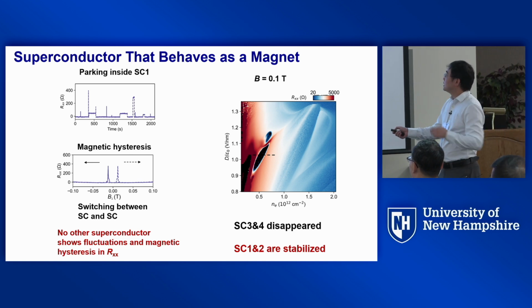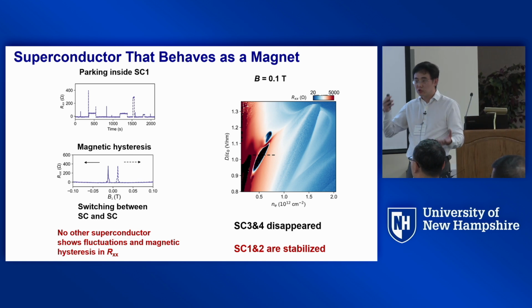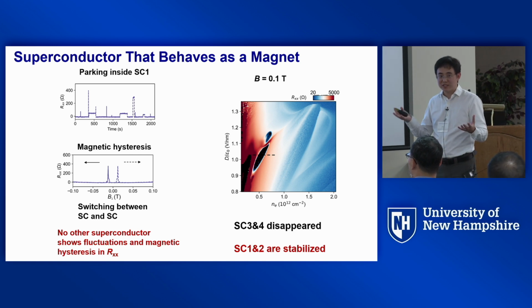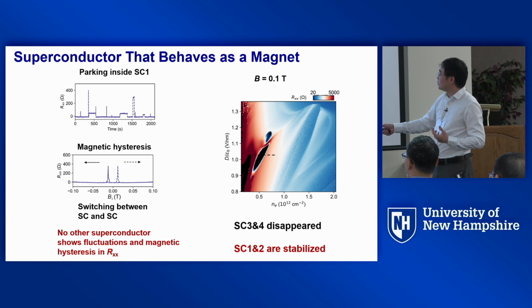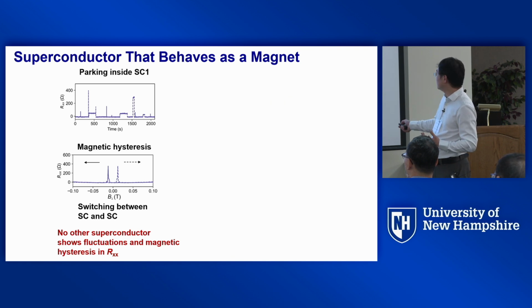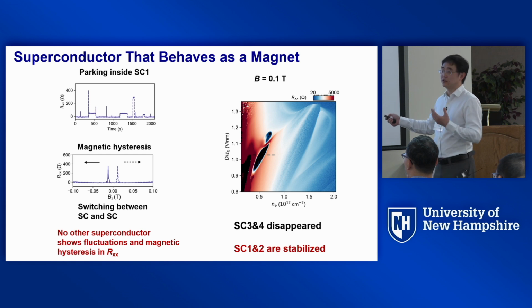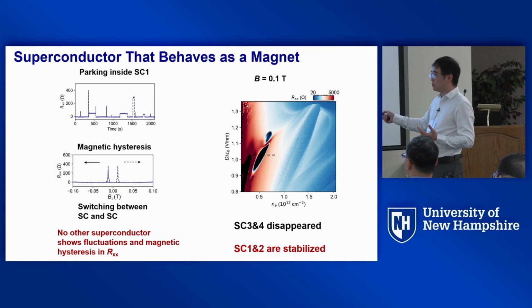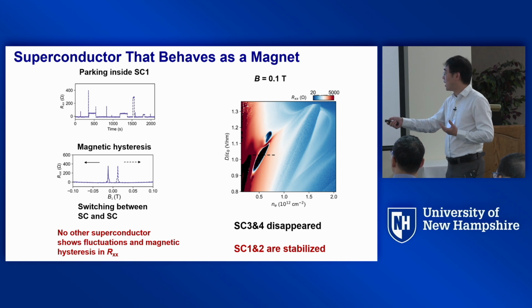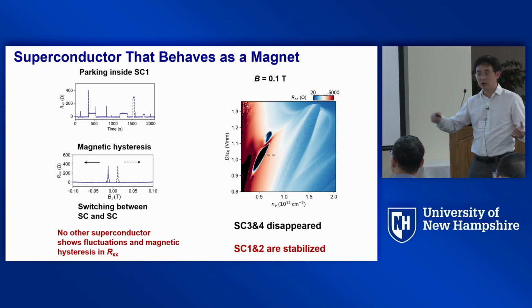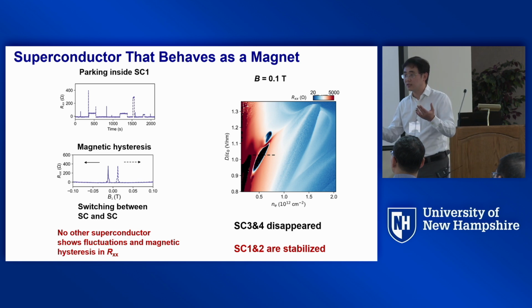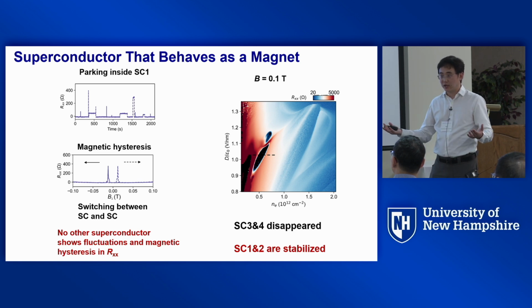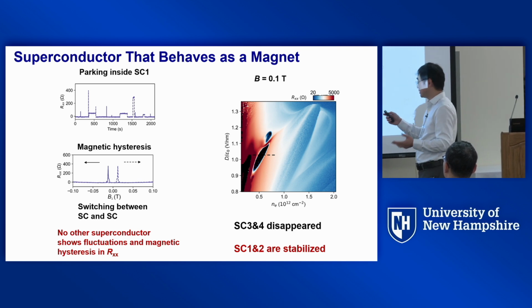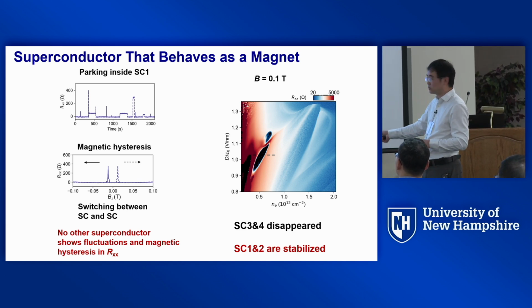Basically, we're talking about the magnetic hysteresis, or switching between two superconducting states. I'll tell you what these two superconducting states are later. As you can see, when you apply something like 100 millitesla, much bigger than what can kill SC1 and SC2, instead of killing the superconductivity, you stabilize it. Remember, SC1 and SC2 have a lot of fluctuations, and there's also fluctuation nearby. With 0.1 Tesla, beyond this coercive field, everything got stabilized. There's no more fluctuation. It's really like a magnet that you polarize in one way, and it just stays like that. But if you go to 0 magnetic field, thermal excitation can, from time to time, flip it. This is why we think this is somewhat like a magnetic superconductivity. That's a perpendicular field.